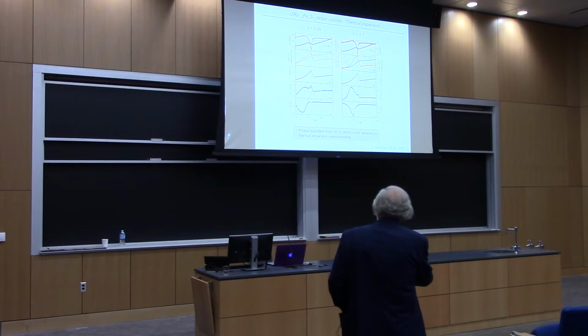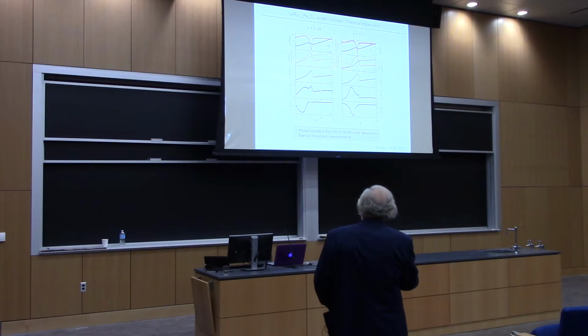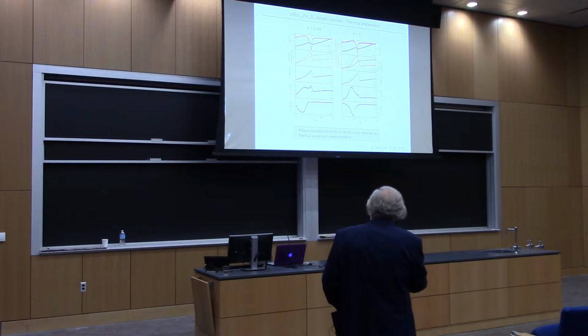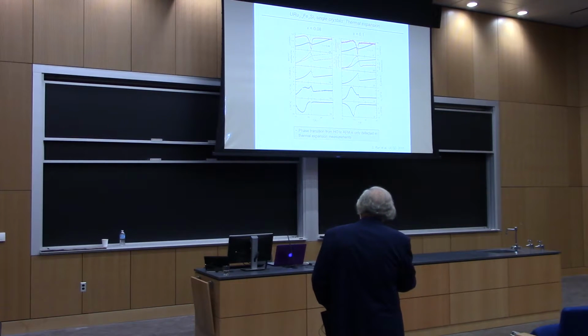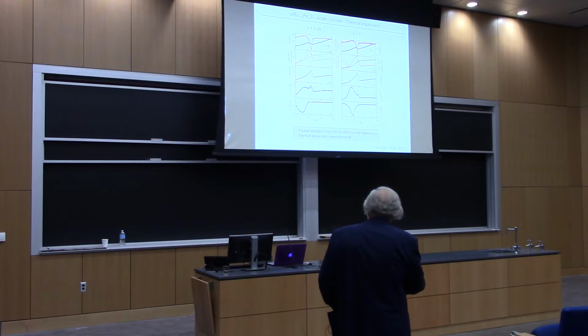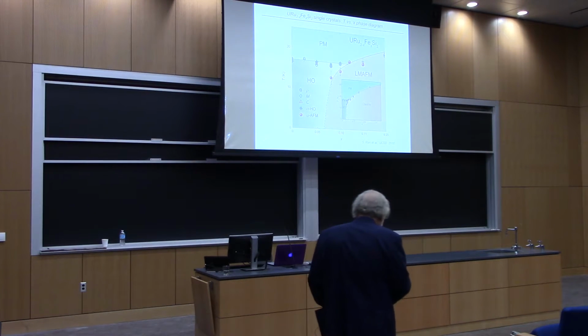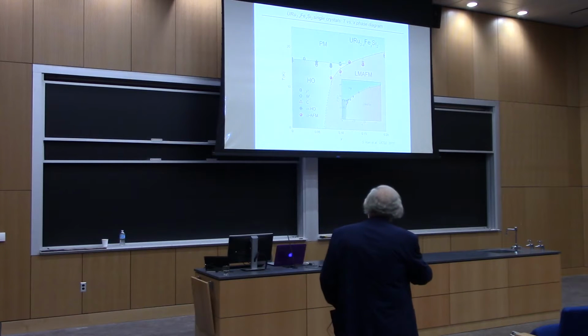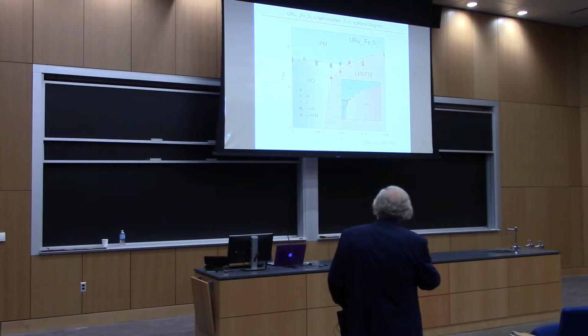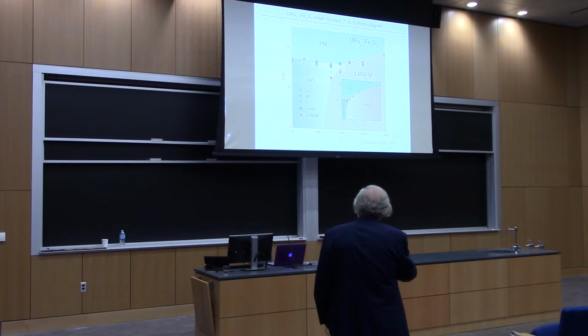And so this shows these data in more detail. We don't see very much in resistivity and magnetization and specific heat, but in thermal expansion you do, so you see two features in these two samples. And then if you construct phase diagrams from all of these data, again it has a kink where you go from hidden order to large moment antiferromagnetism, and then you see that this phase boundary is not vertical, similar to what occurs under pressure. And these two samples are the ones that have other conditions. So we want to explore this further with thermal expansion and also neutron scattering.